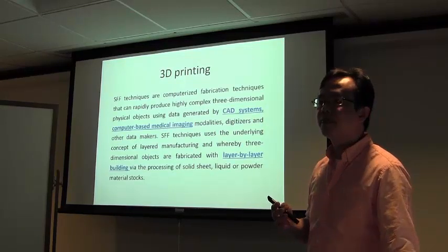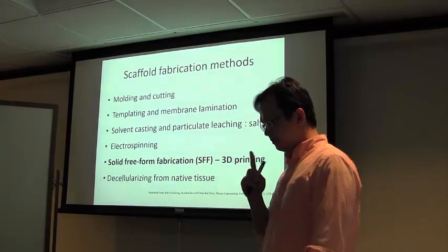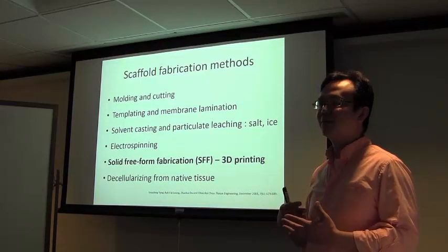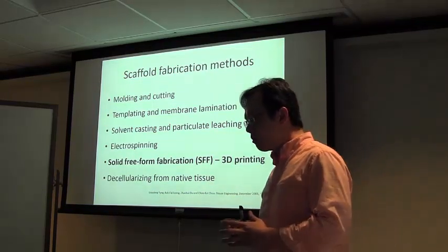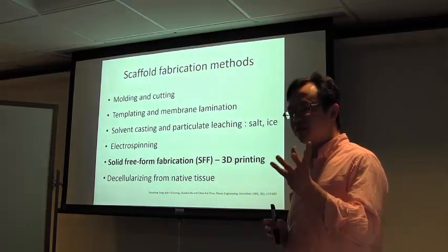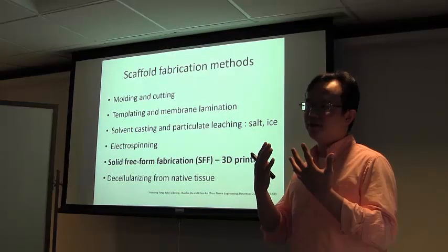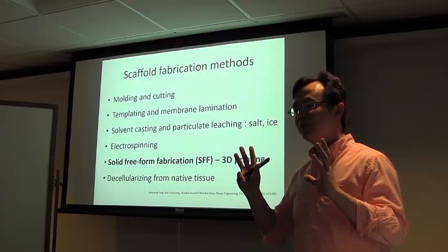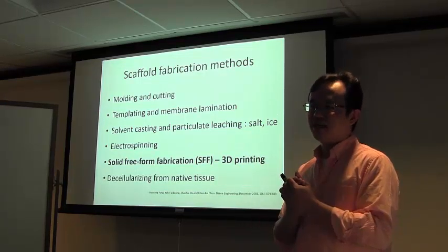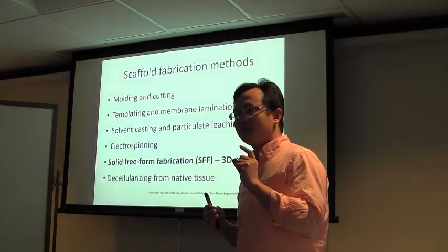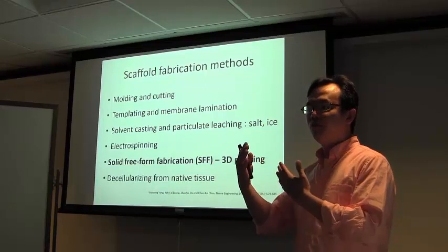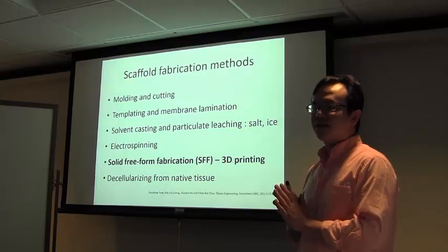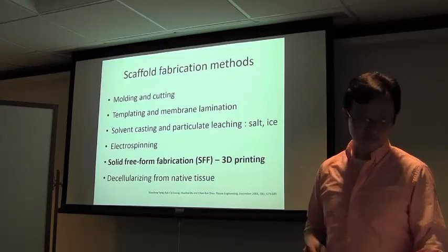But decellularizing can be very powerful. Let me answer your question. In our lab, we also work a lot on decellularized matrix. The problem is that it's very soft. If you take a heart or liver, once you decellularize it, the shape doesn't change, but the inside structure is destroyed. That can be a problem. A second problem is how you're going to reconstitute the scaffold you made. So nothing is perfect, but we can work on both ways. Good question.